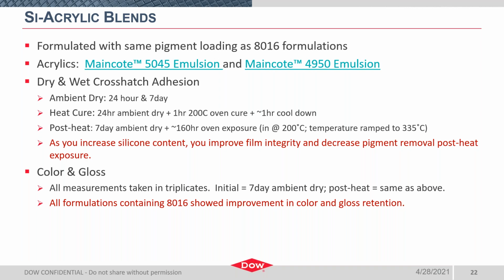Simply put, as you increase the silicone content in either acrylic emulsion, you improve the film integrity, the adhesion, and you decrease pigment removal or improve cohesion post-heat exposure. And all formulations containing 8016 did show an improvement in color and gloss retention. Of course, all of this is expected. As you add more silicone, you have better heat resistance. So I'll share now the level of improvement.